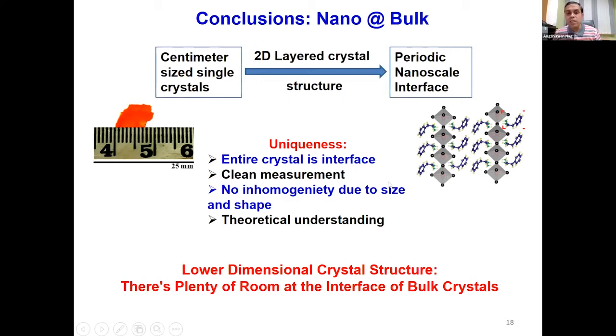And then we can do all these measurements from one single crystal. So we get a very clean measurement, without the uncertainties of size, shape, etc. And that will probably also help our theoretical colleagues to understand the structure-property relationship in a better way. In today's example, I took a layered hybrid perovskite, but there are many other such low-dimensional materials. For example, even with transition metal dichalcogenides in the 1970s, there are examples of playing with intercalation of systems like tantalum sulfide, and playing with the nanoscale interaction between the layers in an attempt to improve the superconductivity parameters for those systems.